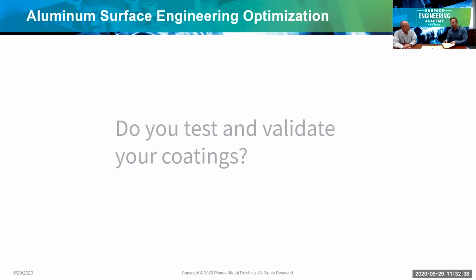Next question. Do you test and validate your coatings? Yes, we do. So as far as what's really critical from an operations standpoint is understanding all the different inputs that have an impact and all the synergies that are involved, whether that's control of the chemistry, whether that's control in the dwell times and the different tanks, the temperatures. We have formal control plans that we've developed over the 50 years we've been in business. And then we go and measure the outputs that are critical, whether that's wear resistance, corrosion protection, the thickness range that's required. That's done not only on a job-by-job basis, but we also do performance testing to make sure that no matter whose parts come in, when we say we're going to do type 3 hard coat, we're going to meet the wear resistance requirements.